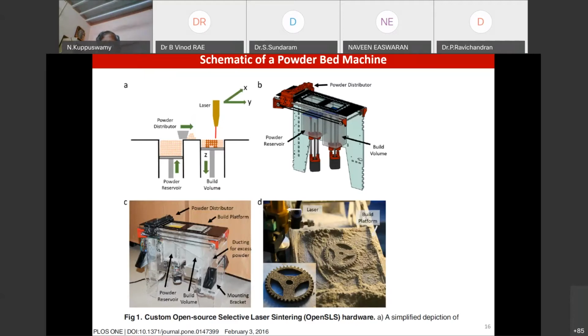Now, when you're dealing with parts which are used, for instance, if you're trying to make a medical implant and using a nylon part as a reference, so that you show it to the surgeon and the surgeon approves it for that particular patient, then you cannot go through the inexpensive methods of making a plastic part by the wire process. Because the kind of accuracy you get in SLS for nylon or PEEK is very high and gives a clear picture to the end user as to what the finished part is going to look like. It's very critical because otherwise if the design input for the implant from the surgeon is wrong, then even the metal implant will be wrong. But for that, the surgeon has to understand, and you cannot expect a surgeon to understand the limitations of 3D printing. Therefore, you have to give him a part which is almost true in nature. That's where SLS comes in.